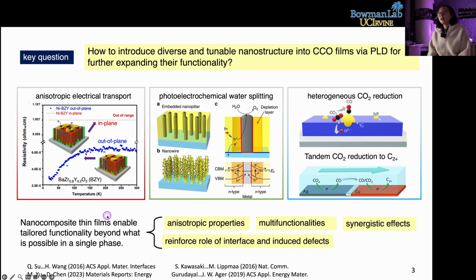in electrochemistry devices. Because the nanocomposite can provide anisotropic properties, multifunctions, synergistic effects, or reinforce the role of interface and induced defects. For example, Professor Wang's group developed a vertically aligned nanostructure to achieve anisotropic electric transport. They introduced nickel vertically aligned nanostructure into oxide films, and they found the in-plane conductivity is totally different than the out-of-plane. So the electronic transport pathway is totally different in these two directions.